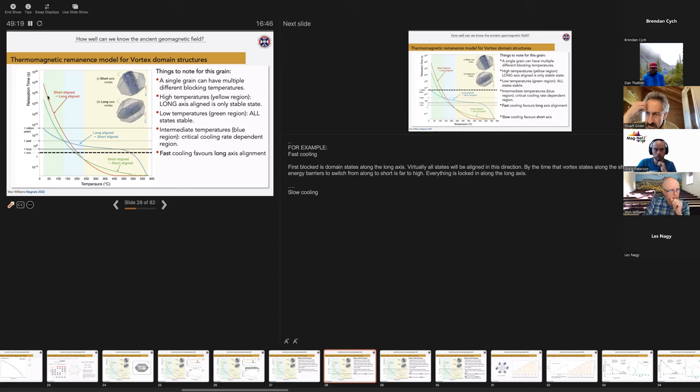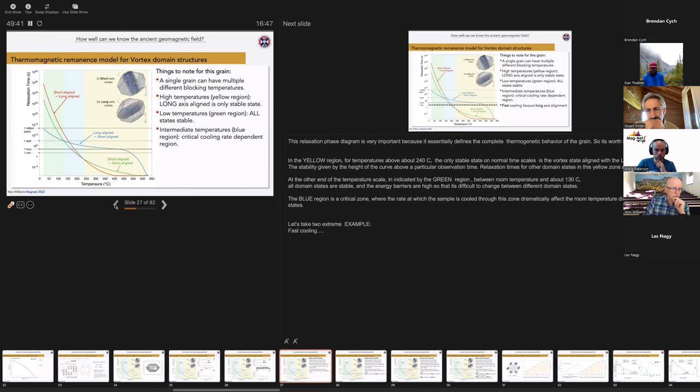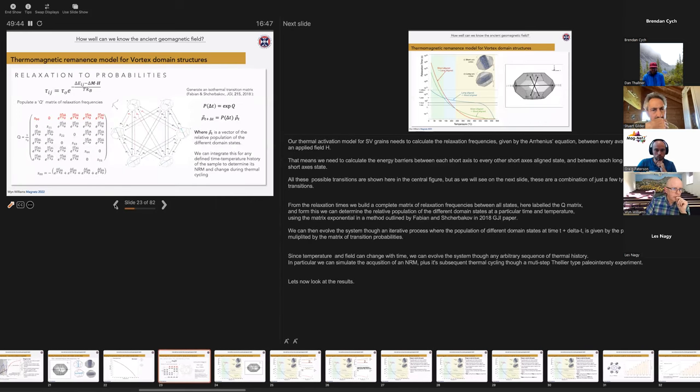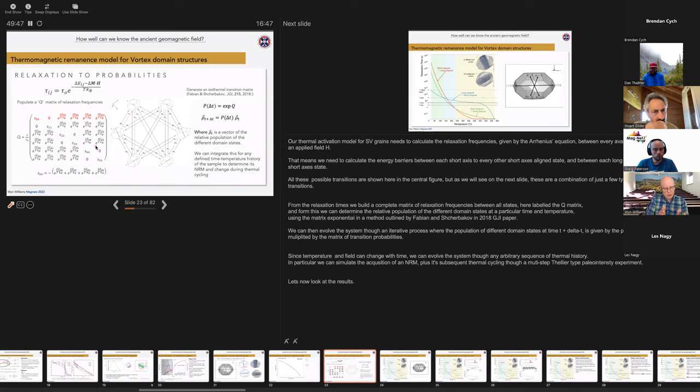Of course, this is just one example. There may be many explanations for such magnetic behavior. But it's likely that these fine grain basalts actually do contain PSD grains. And at least it is consistent with the observations and predictions that we make. So I've covered a lot of ground. I've gone way over time, which I apologize for. I'm just going to summarize the results in four short slides. So we've built a thermomagnetic model for PSD grains that accounts for any thermomagnetic history. It predicts this failure of reciprocity. So the blocking and unblocking temperatures are quite different. That results in PTRM check failures can result in PTRM tails. It arises when different domain states with similar energy barriers are possible in one particular grain.